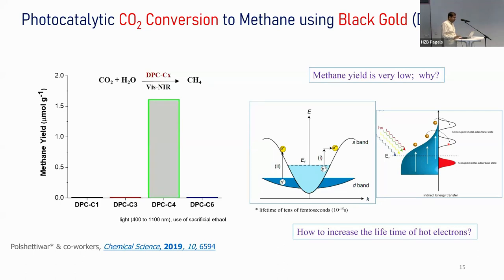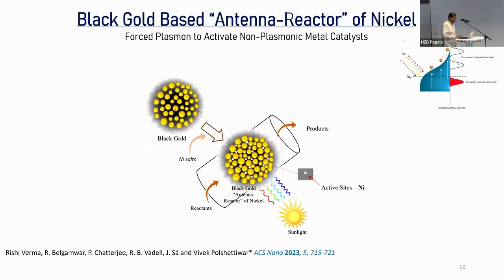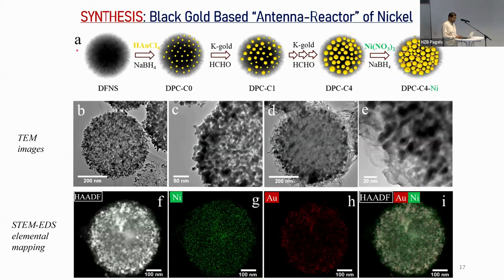In order to study this, we prepared such a material. We took the black gold, loaded with nickel nanoparticles, which went onto the surface of the gold as well as between the gaps of the gold nanoparticles, where we have these hot spots. And then we tried to evaluate them by CO2 reduction reactions. So synthesis was straightforward. You make a black gold, load with a nickel nitrate salt, reduced by sodium borohydride. We also did one more reduction during the catalysis by using hydrogen gas to avoid any oxidation of the nickel. First, we wanted to see how the nickel nanoparticles are, what is their size, how they are dispersed.